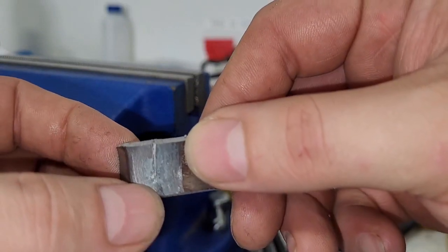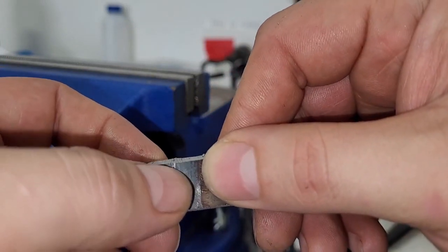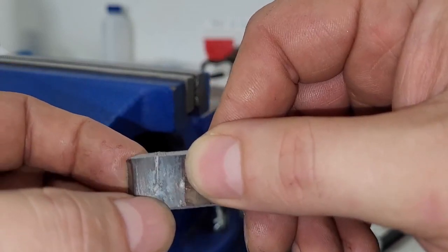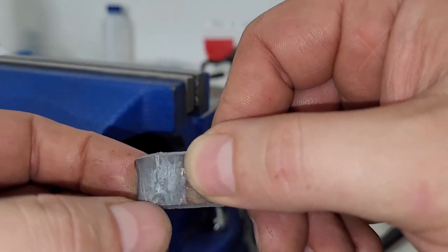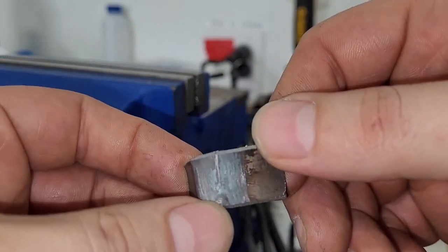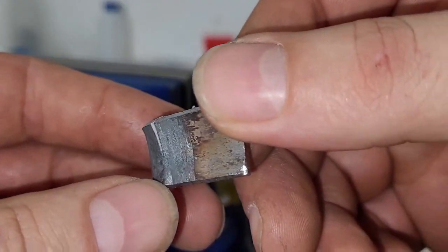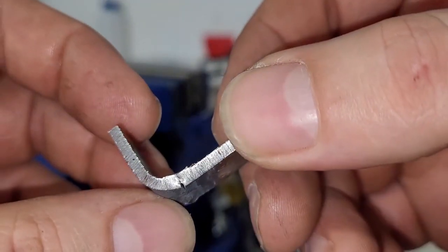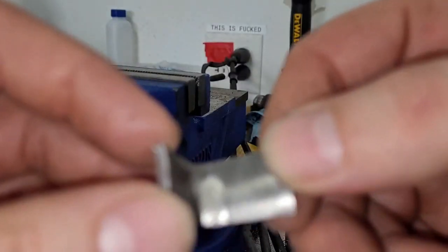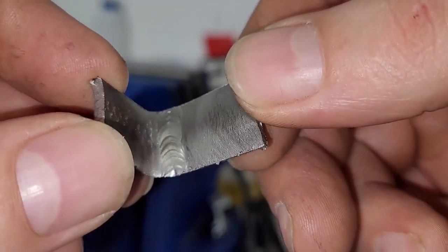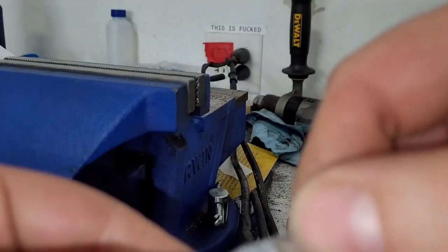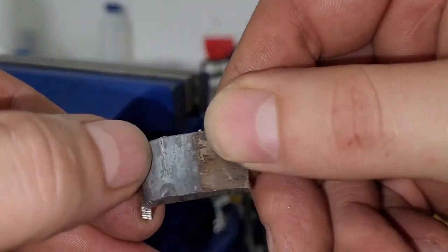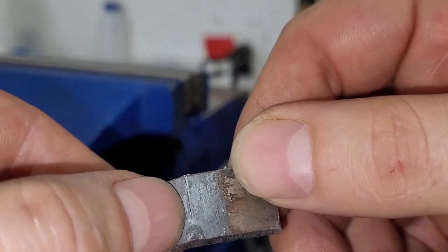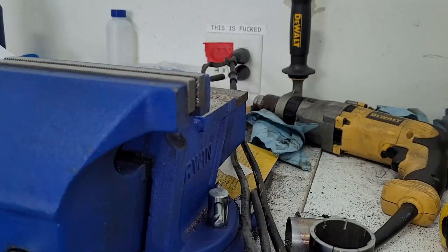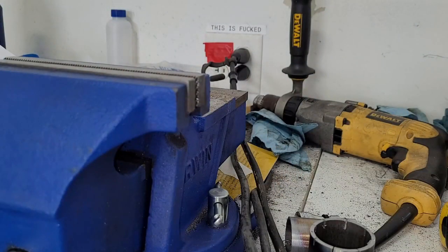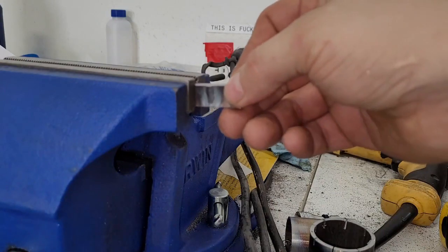You can kind of see it cracked where the weld had not made it all the way through the material, and the crack ran down, and actually the crack stops where the weld is. So, kind of interesting. Here's the welded side. Looks good. So that's kind of what you would think. You don't get full penetration, and then you try to rip the weld open and it tears. So this kind of tells me that the second samples we did are probably going to be worse, not better.